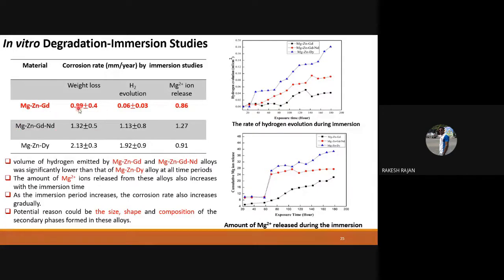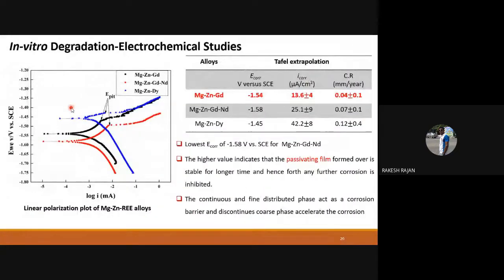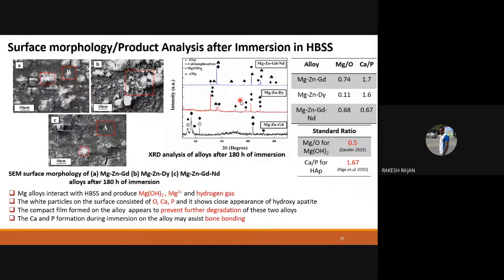That means 0.99 mm per year weight loss is happening, and this is also supported by hydrogen evolution and magnesium ion release data. So these are the two supporting documents to give the weight loss value. We are collecting the data to understand how the corrosion rate or degradation is happening, and the direct electrochemical studies also gave the same kind of trend, with the magnesium zinc gadolinium combination having a better corrosion rate. After that, you need to understand the surface morphology.